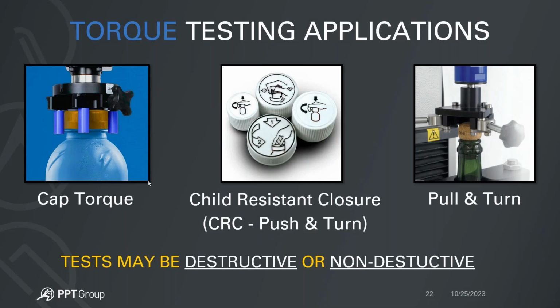That means the capper is not applying uniform torque. Because usually these cappers, whether they're pneumatic or hydraulic, are applying uniform capping or application torque to these caps. Let's say it's between 10 and 12 inch-pounds of torque. When you grab a handful of samples and put them in a tester and run release torque, as long as that torque range is consistent, you'll also see release torque values that are consistent.